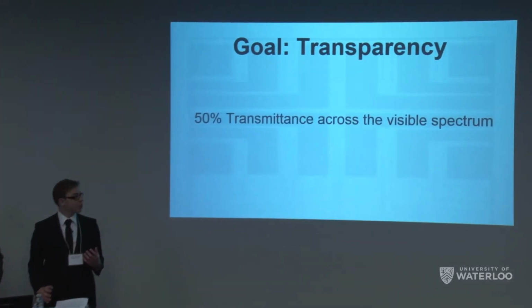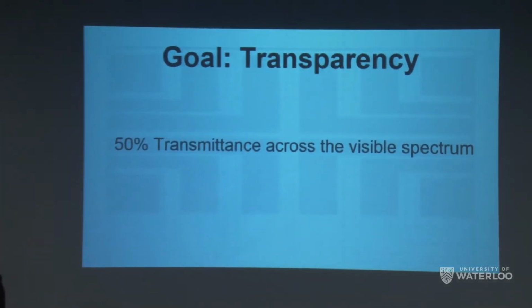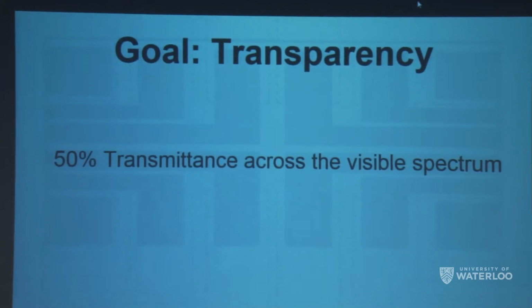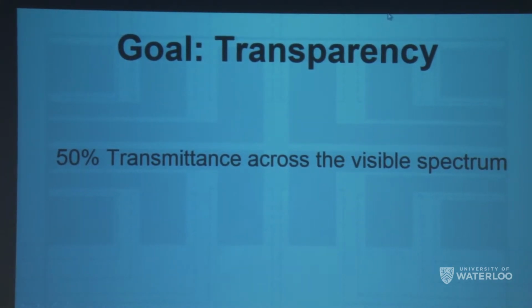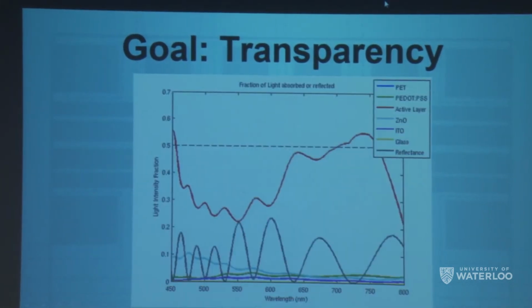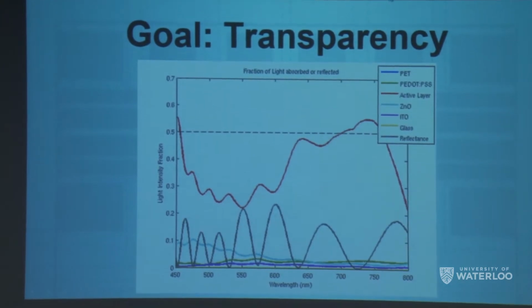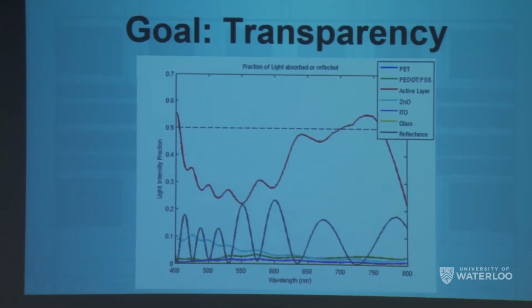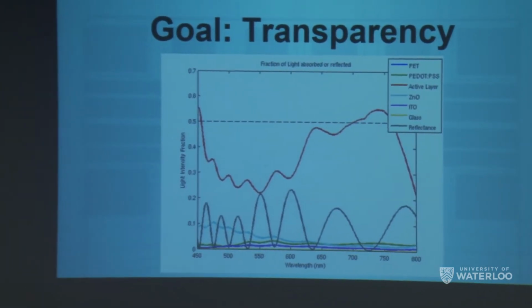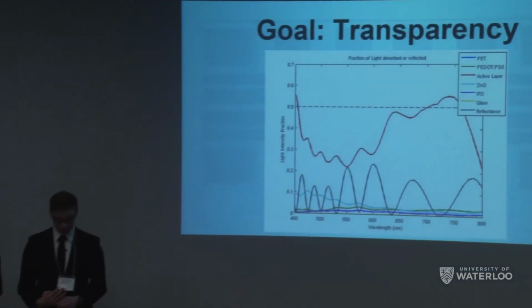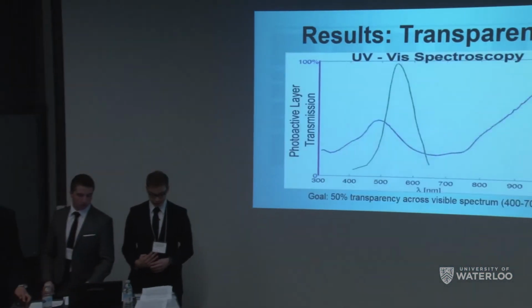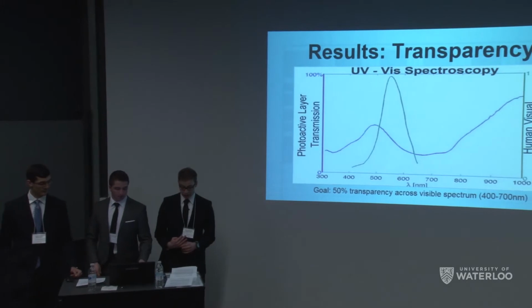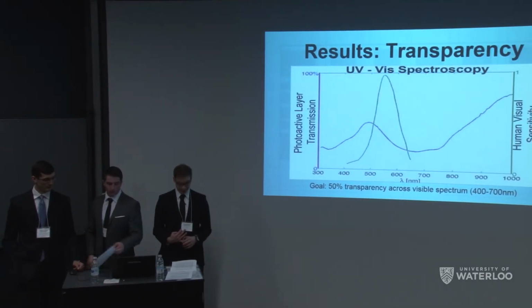So our transparency goal for this device was to allow 50% of light at every wavelength across the visible spectrum to pass through the device. We ran a simulation, and for our specified layer thicknesses, this device should have only absorbed a little bit in the red portion of the spectrum. To validate, we fabricated the device to spec as best we could and ran it through a UV-vis spectrometer. Though this device did not work electrically, its optical properties are still valid.